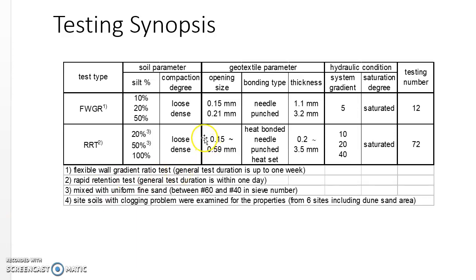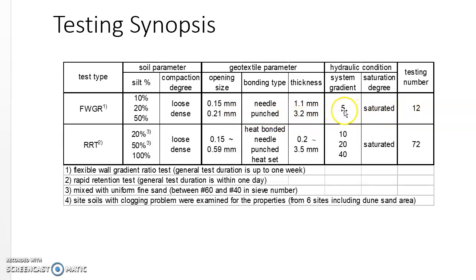I have investigated geotextile filter performance using laboratory tests. The first is called the Flexible Wall Gradient Ratio test, abbreviated as FWGR, and the second is the Rapid Retention Test, abbreviated as RRT. The flexible wall gradient ratio test is known as the best available technique to examine the clogging process of geotextile in real time, but it takes a lot of time — up to seven days. To compensate for that long test period, I also tested using the RRT, Rapid Retention Test.